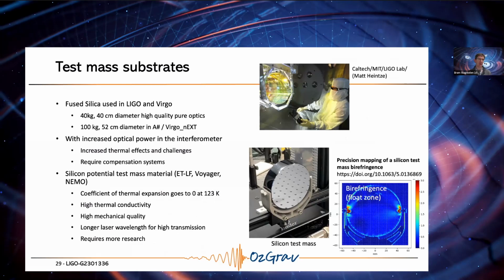Then for the not too distant future, the A-sharp scenarios are all still using fused silica, as we're using that. Now on the top right, there's a beautiful picture of one of those test masses in LIGO. However, we're going from that 40 centimeter to about 50 centimeter diameter test masses, and about 100 kilograms, so it will be a whole new challenge, of course, to operate those devices and suspend them from the suspension system.